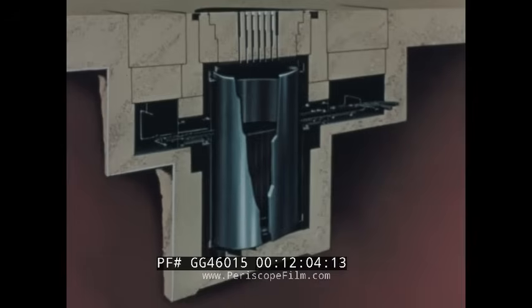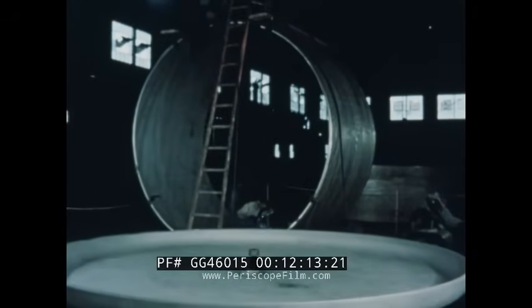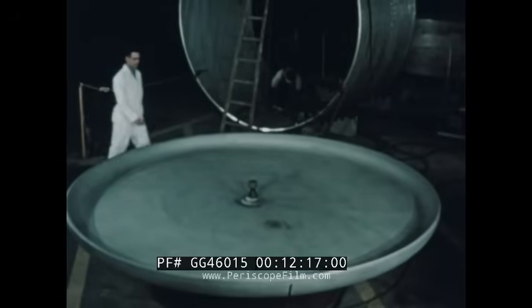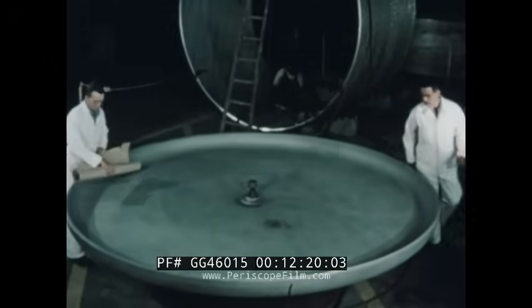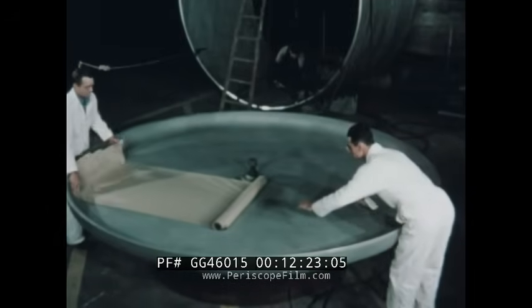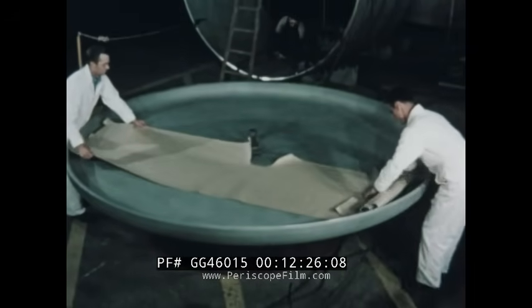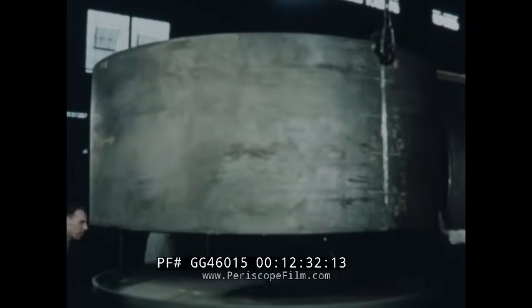The core tank is 19 feet deep and 11 feet in diameter. Made of 304 stainless steel, it has a wall thickness of 1.5 inches. The bottom head was formed cold and specially heat-treated to maintain the required close tolerances. Prior to fabrication, all material was ultrasonically inspected for internal laminations and voids. The sides of the tank were built of 3 ring sections, each welded in place. All welds were given dye-penetrant and X-ray inspection.